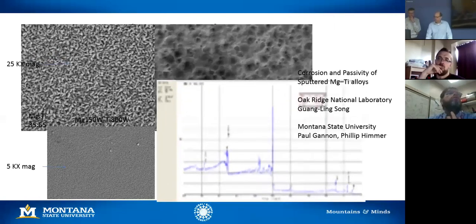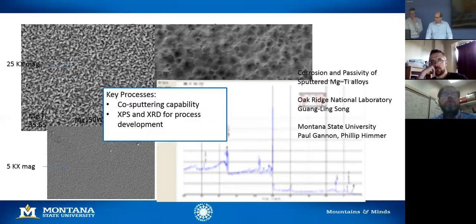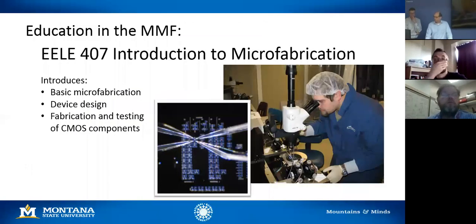His students went over to ICAL, and with the help of the ICAL staff, were able to take this data from the XPS, go back to the sputter system, and adjust parameters until you get the alloy that you wanted. So the co-sputtering capability combined with having XPS, and also using the XRD in this project, allowed us to do this work for Oak Ridge National Lab, which was a nice project.